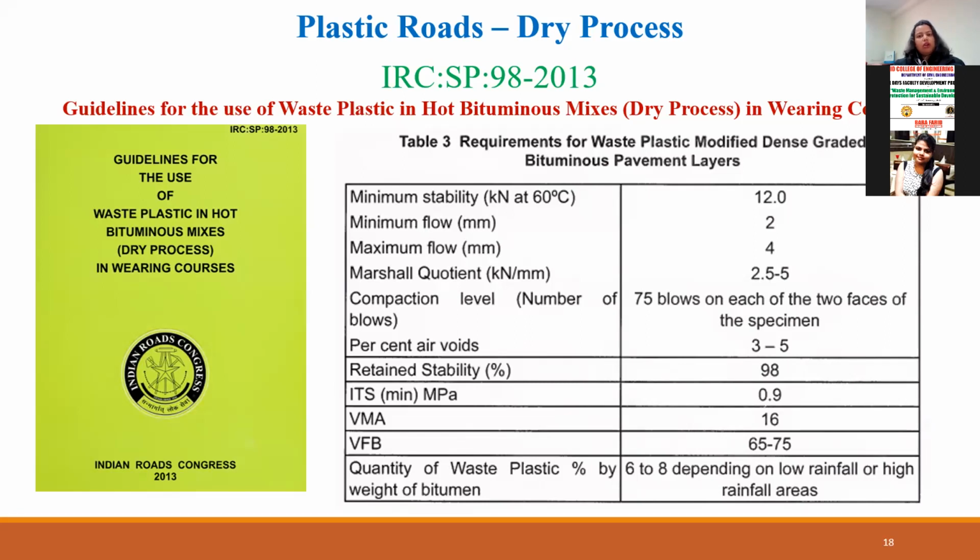So in areas with higher rainfall, higher snowfall, and higher freeze and thaw action, say like Leh, Ladakh, or areas where you have border roads, you need a larger quantity of bitumen replaced with plastic waste. So instead of going with the lowest possible 6%, you may take it a little higher, till 7%, which you can also try in your laboratory.